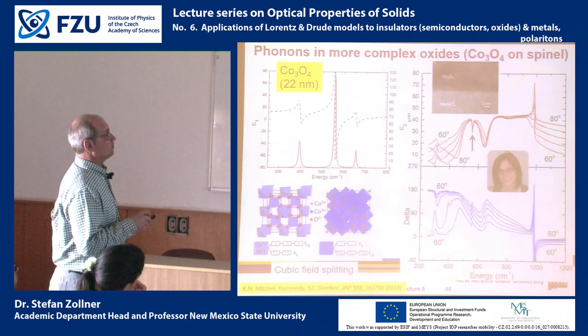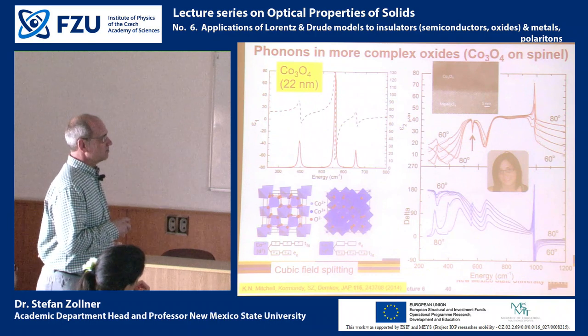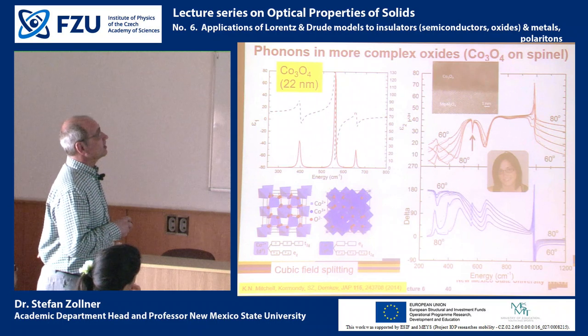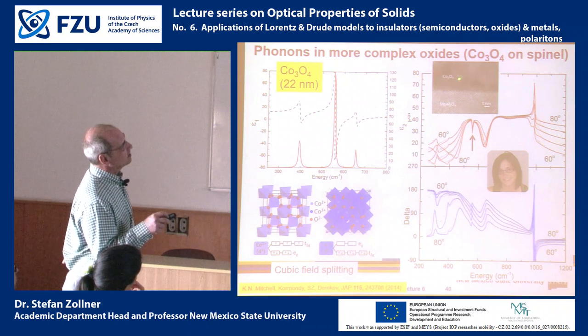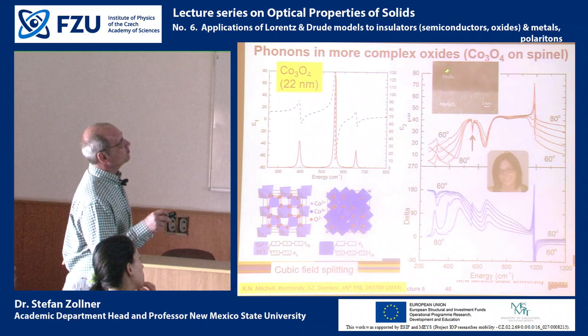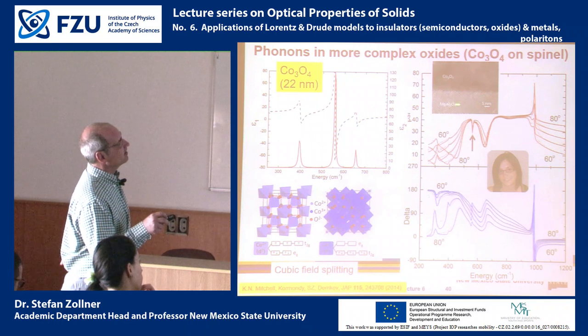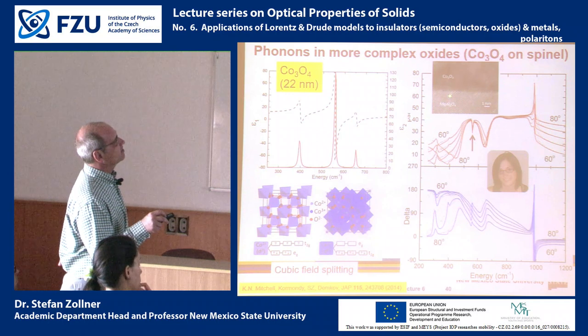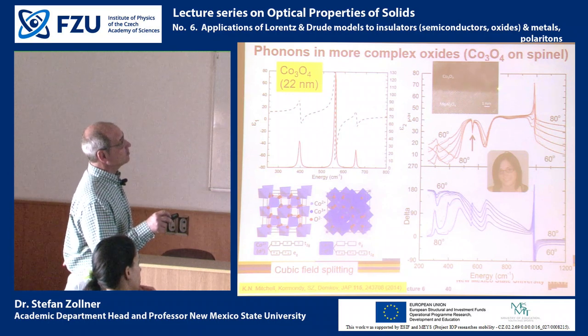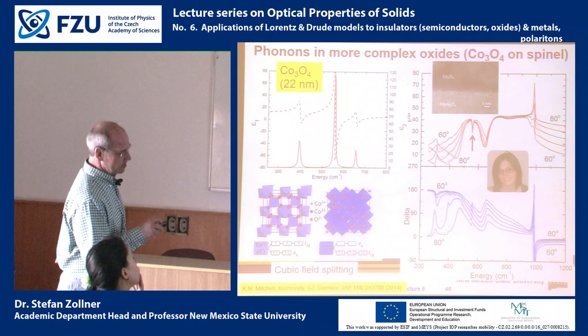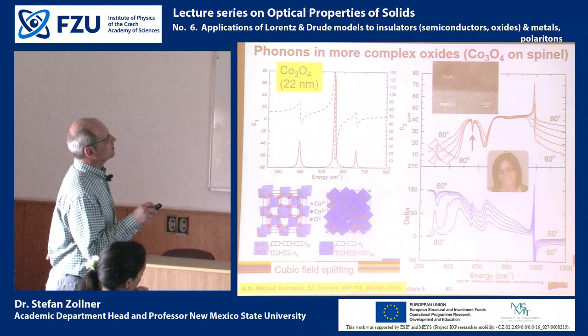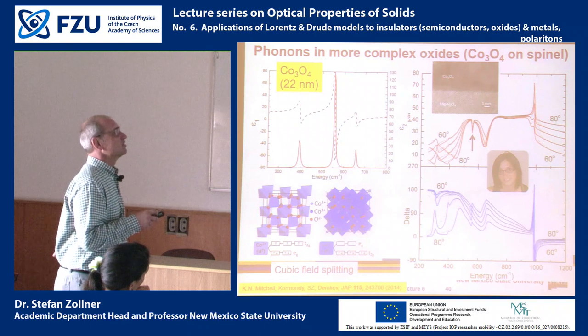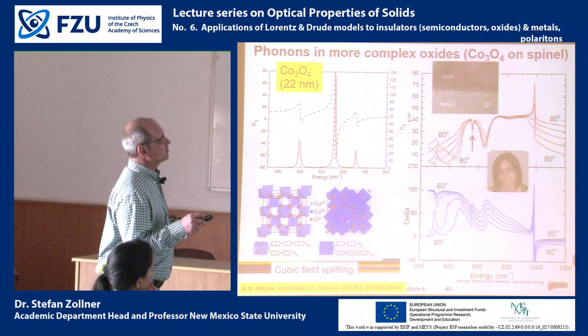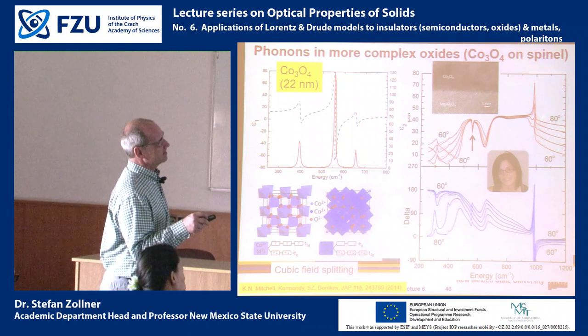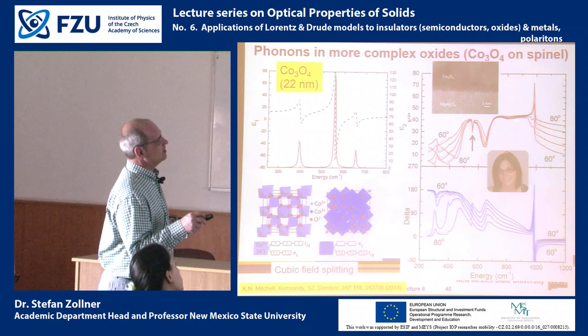The examples that I've shown so far were all for bulk crystals. But, of course, it is also possible to study thin films. This material here is cobalt oxide Co3O4, a cobalt spinel on a magnesium aluminate spinel substrate. This is a transmission electron micrograph, which shows a very nice interface between the substrate and the epi layer on top. The thickness of this cobalt layer is 22 nanometers. And if we look at the ellipsometric spectrum, this here is the ellipsometric angle psi, then primarily this spectrum is the same as for the bulk spinel.